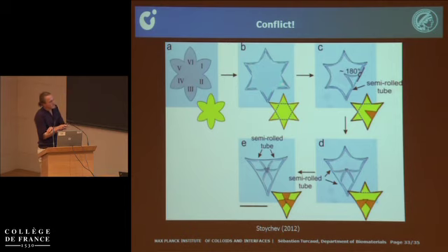Maybe because of imperfections in the material or little changes in diffusion, one of the wings will start to fold, and the folding will erase those two weak points. Once this wing has folded, those two cannot fold anymore. The next possible one is this one, and that's what we see here, and then the next possible one would be this one. This also explains why this is the most observed pattern.